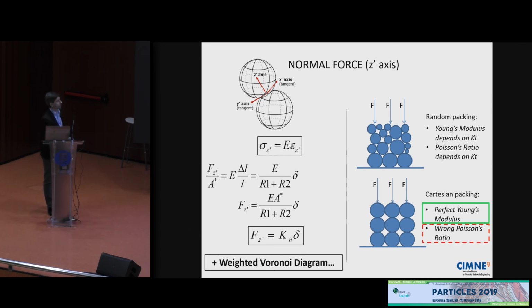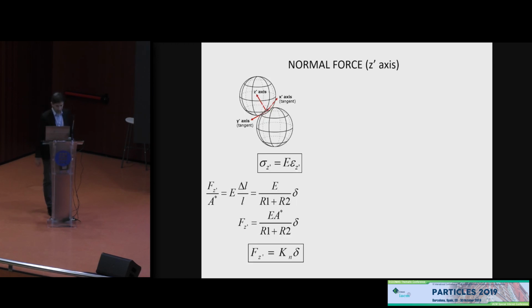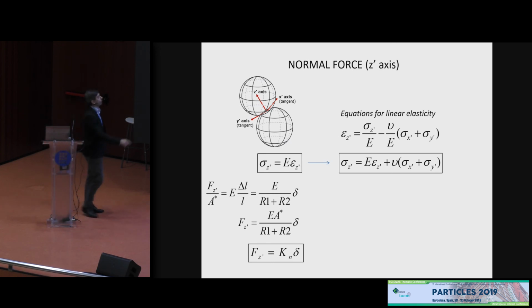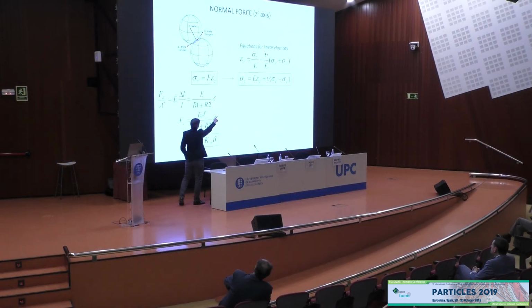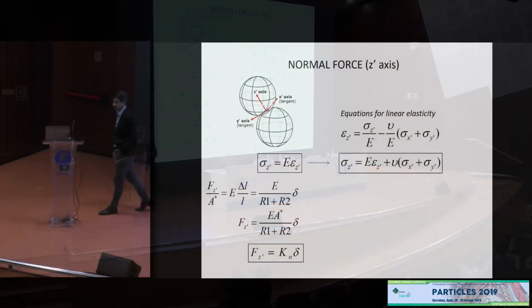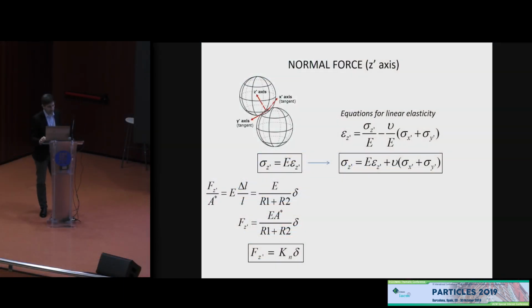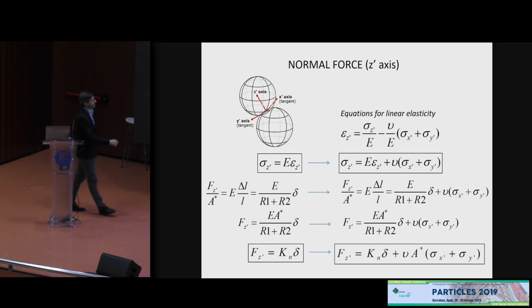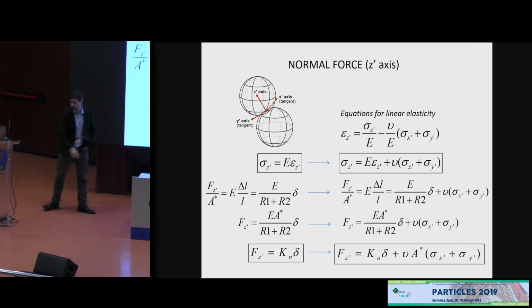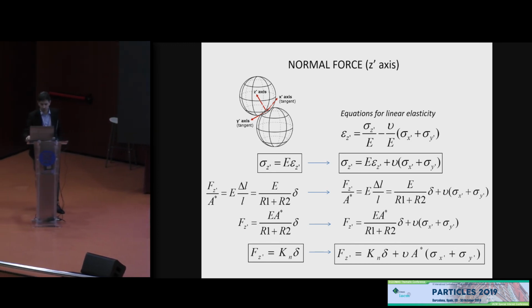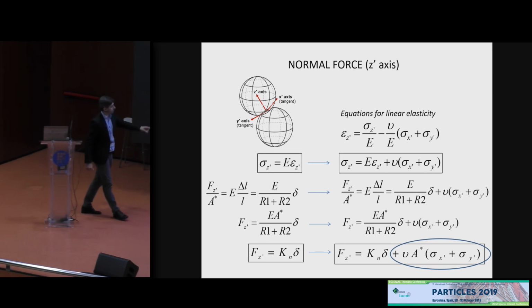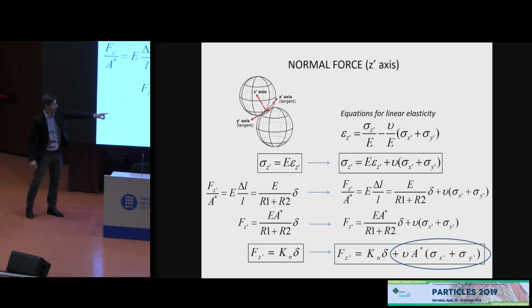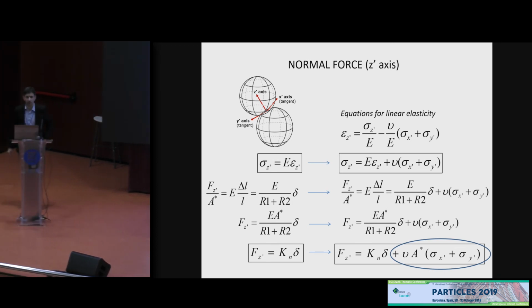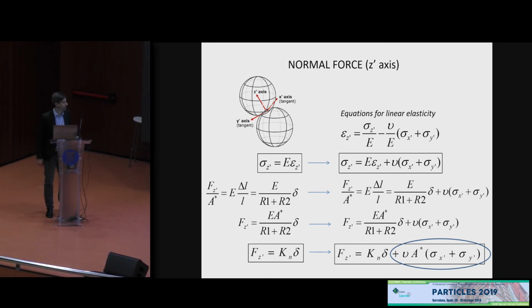So let's work on that red square. And the idea is to change these equations, and instead of using a 1D elasticity equation, we will use a 3D elasticity equation, because it's a 3D problem. Now, if you do the same substitution, exactly the same step, you end up with a formula that tells you that the normal force between two spheres is something which is in the traditional DEM plus an extra term which depends on the stresses in the surroundings of that bond.